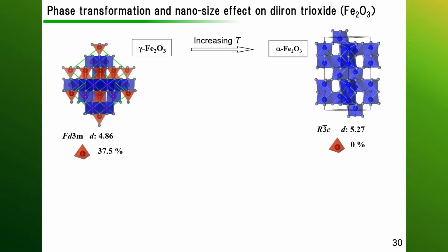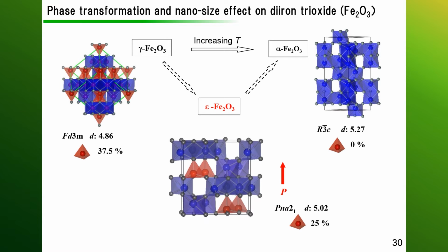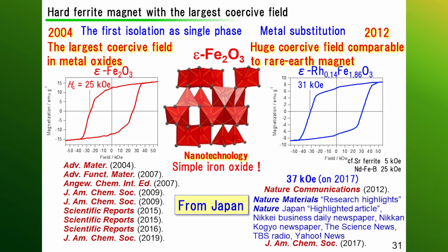Typically, the changes occur as a result of changing crystal structure from gamma to alpha, but we achieve this with nanoparticle epsilon Fe2O3, which exhibits new crystal structures that are usually not visible. This is a nano-sized effect. Between 3 to 50 nanometers, the structure is most stable. The discovery of this new crystal structure was good, but there is a huge magnetic hysteresis loop.